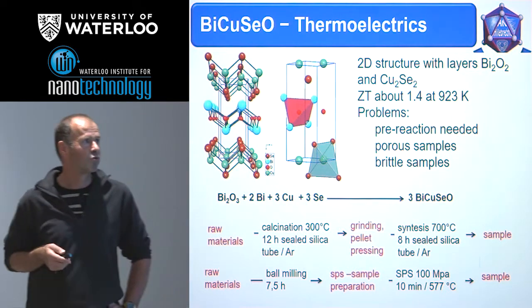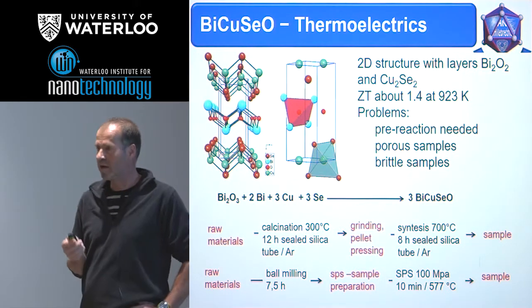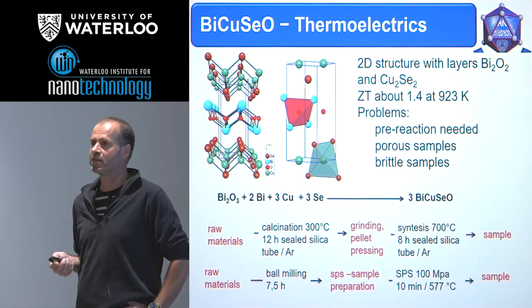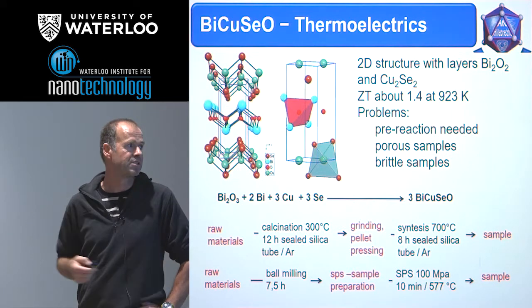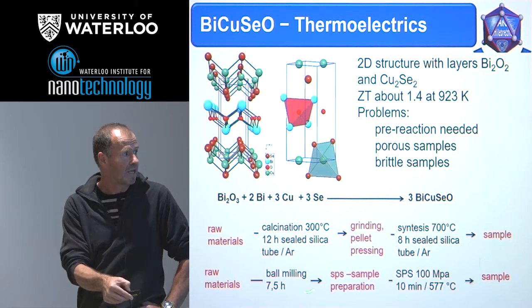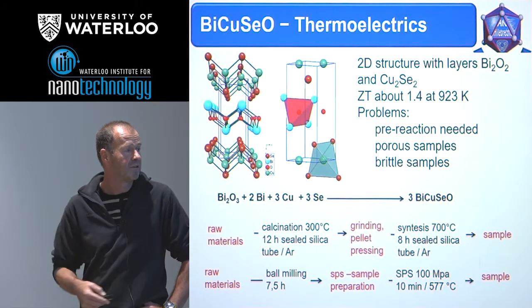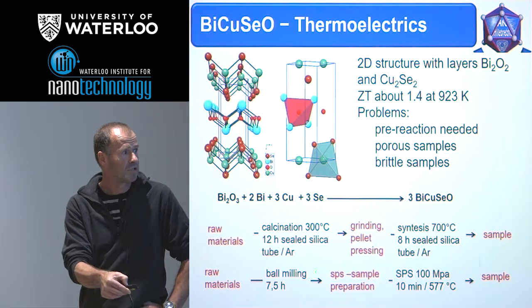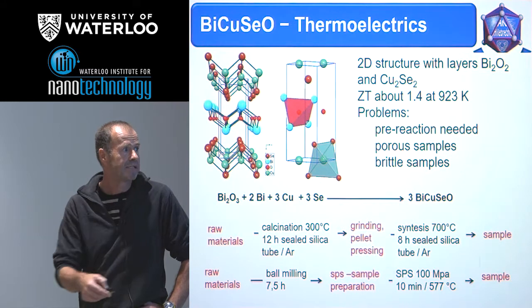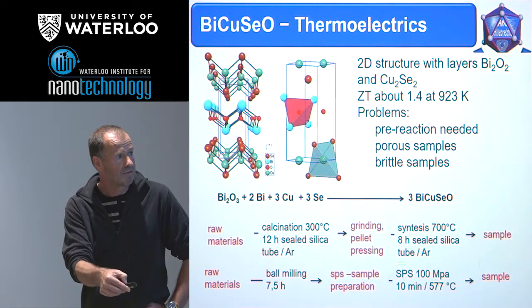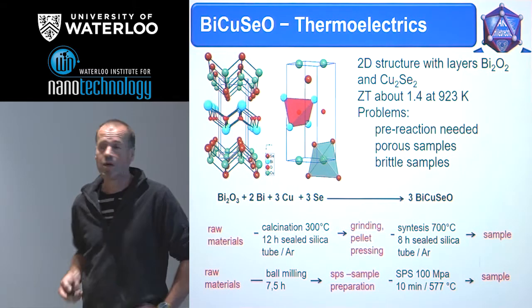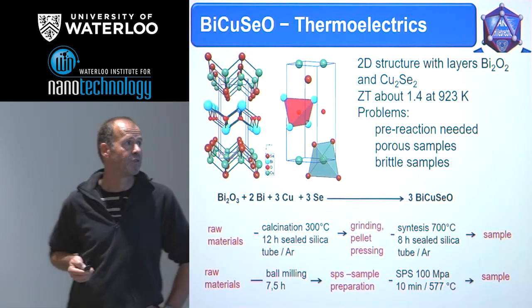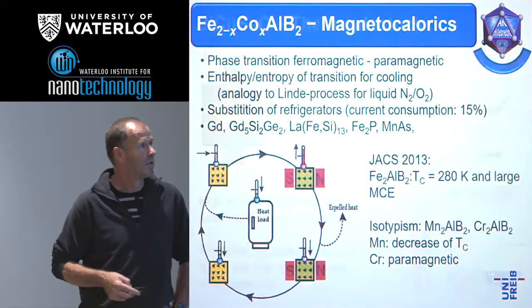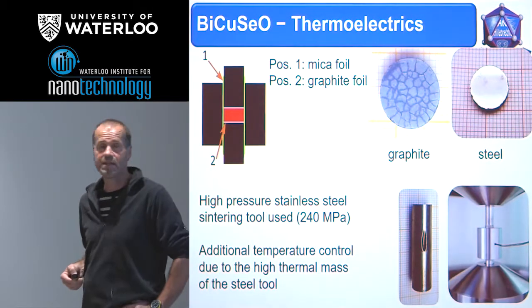And so we tried to develop a one-pot strategy or a one-step synthesis, and indeed, starting with the ball milling of the raw material, we could do it within one step, SPS samples at well-defined conditions, and we got homogeneous samples. The reason why it was necessary is seen here.